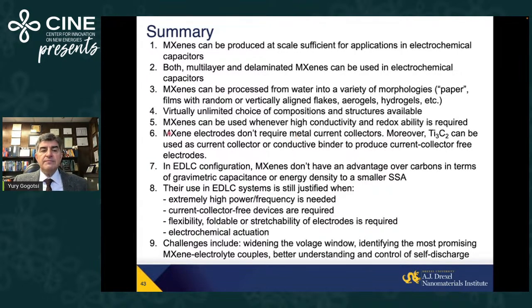Also, you can make current collector free devices, because if you use MXene as active material, typically you really don't need metal current collectors. Or you can use MXene as current collector or binder. And you also need to look at where the limitations are, where the strengths are. For example, porous carbons, activated carbon, carbide-derived carbons, graphene will have the highest specific surface area. So volumetrically, MXene wins. Gravimetric double layer capacitance, carbon will do better because it has larger specific surface area. So you need to select MXenes and use them where they can give an advantage. They're denser volumetrically. If you're looking for a small battery, for example, for a cell phone, you win.